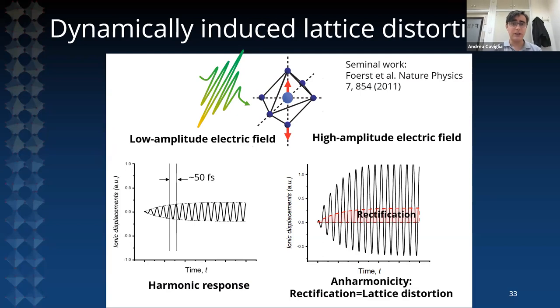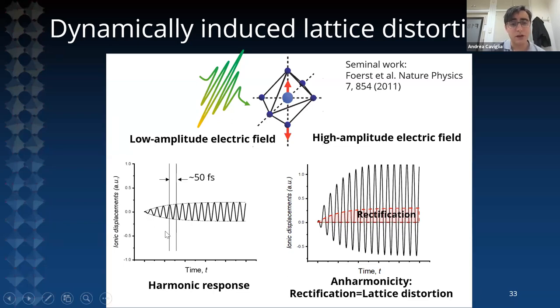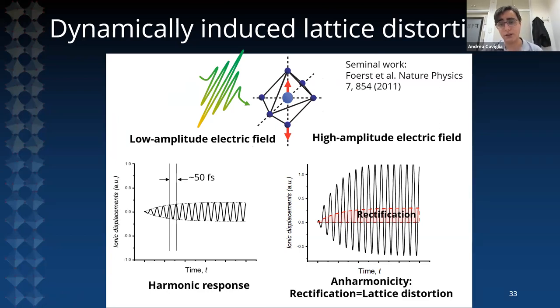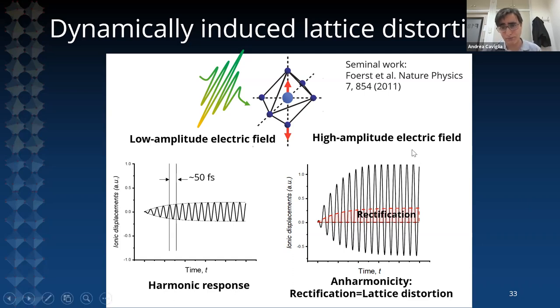What we aim to achieve is to dynamically induce lattice distortions, and to do this we necessarily need to access a non-linear excitation regime. If we remain in a linear response regime, we can only expect harmonic motion and fast decay of any structural resonance. If instead we send a high-amplitude electric field able to access a non-linear regime, it is possible to observe an anharmonic lattice response, which is effectively a rectification of a phonon field along a Raman-active coordinate. This was shown for the first time in the seminal work of Michael Först.